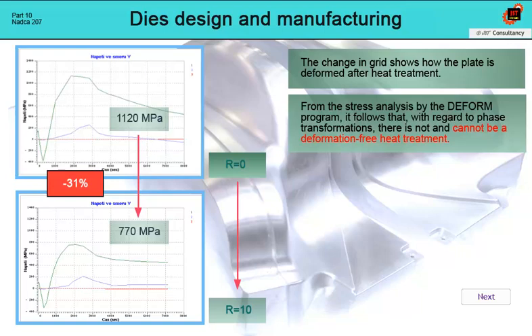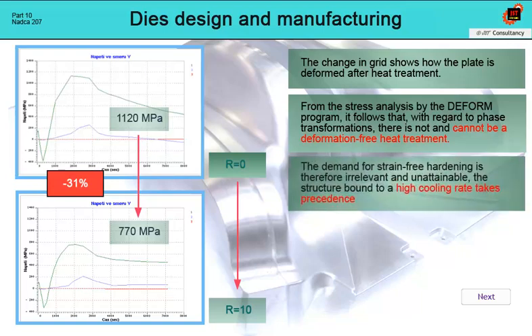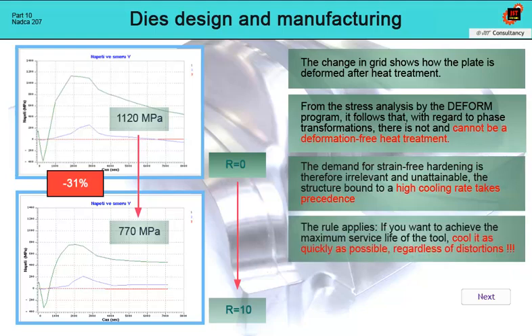It therefore makes sense to prioritize achieving a quality structure and to cool during hardening as quickly as necessary, regardless of distortions. The parts will be deformed as during slow cooling, although a little more, but we will have guaranteed mechanical properties. This is what we primarily need. We just have to avoid catastrophic gross cracks.